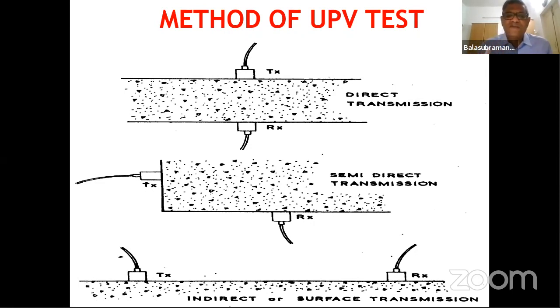For example, you have a retaining wall where the backfilling has already been carried out. Now the client is not happy with the quality of the concrete in the retaining wall. So obviously we cannot go and dig up the entire backfill. At that time, the indirect transmission method is adopted too. But it's a very approximate method. You should try to avoid it as much as possible. And sometimes these UPV tests are even used to measure the depth of a crack, and at that time you go for an indirect measurement. Again, when you measure the depth of a crack through an ultrasonic pulse velocity test, sometimes it gives an erroneous result. So you need to be very careful.